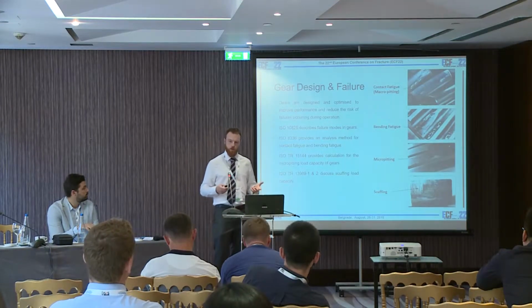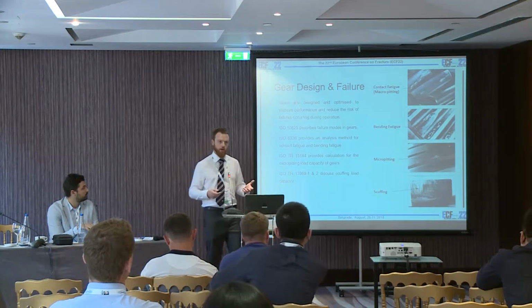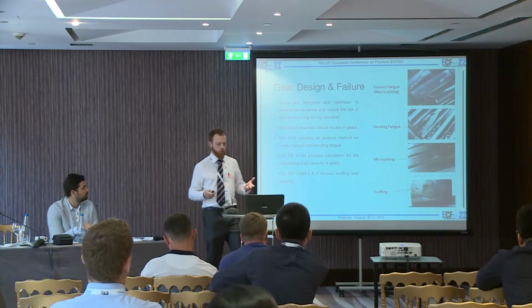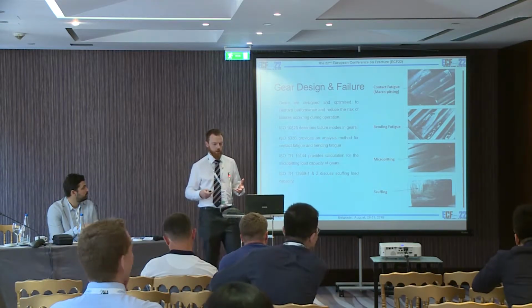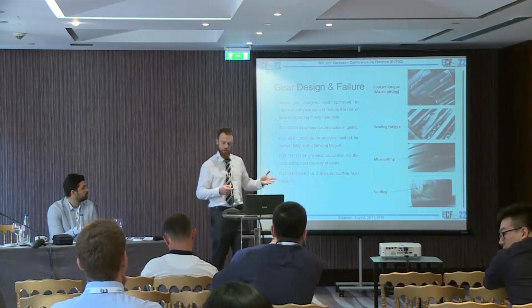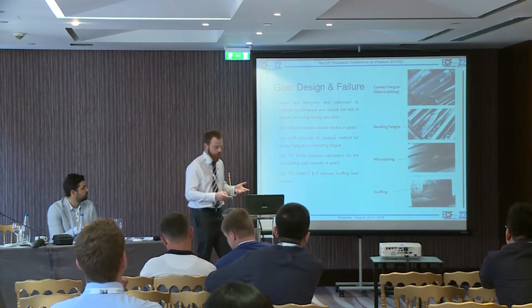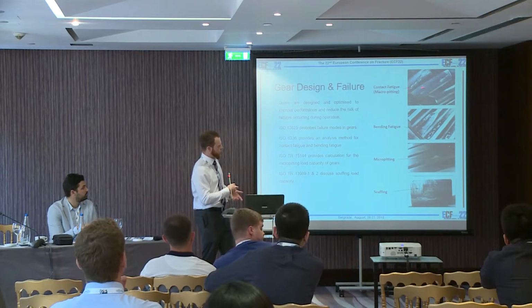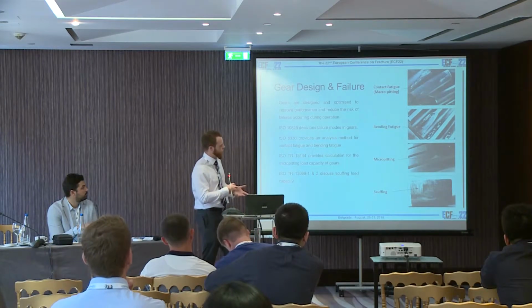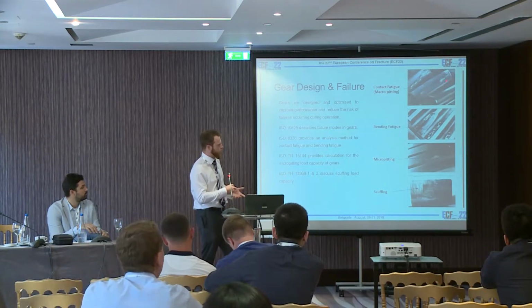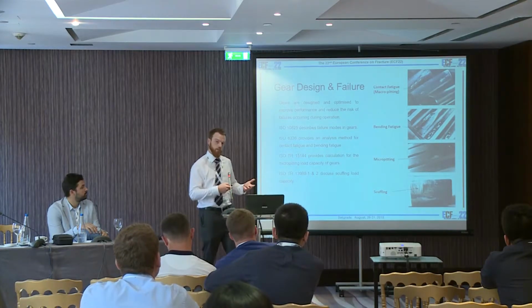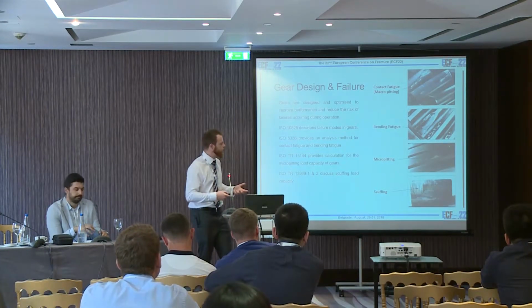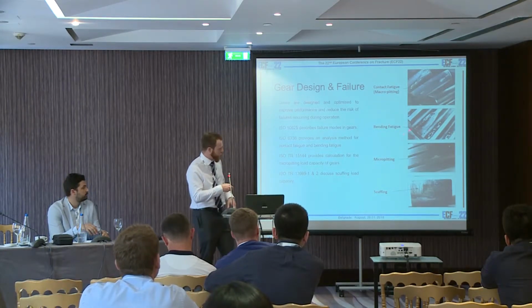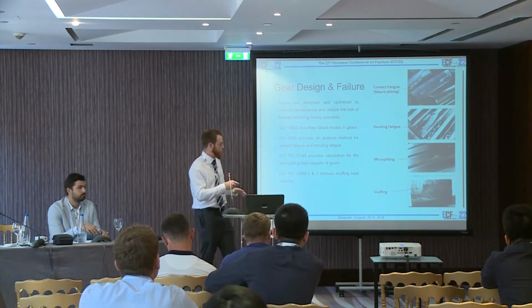So to give you a bit of background in gear design and failure, so we design and optimise gears to improve their performance and reduce the risk of failures occurring during their operation. So there's international standards that describe these kind of failures. I've got a couple of examples here. So we have contact fatigue. So this is driven by hertzian contact stresses. So as the gears come through contact, we have rolling sliding contacts come through. We have subsurface initiated cracks, which then lead to pitting at the surface, and this degenerates the efficiency of the gears. Bending fatigue failure, which I will cover a little bit more about in the next slide.